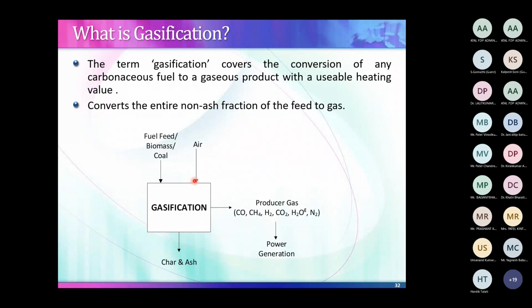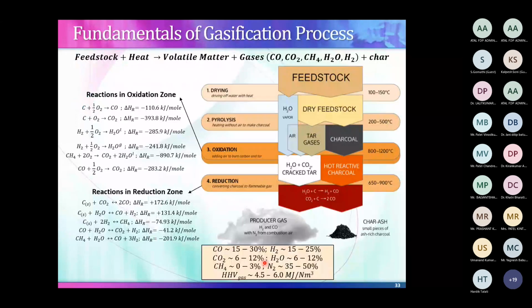Now this gives complete detail, some insight. This gasifier passes through 4 stages. The first is drying, so your feedstock will get dried, temperature is 100 to 150. Then it will get pyrolyzed, that is in the absence of air, it will disintegrate into tar and char. This is at 200 to 500 degrees centigrade. Then we supply partial air, so it will oxidize, producing some heat at 800 to 1200. This charcoal then will enter the reduction zone, where it will carry out a reduction reaction.